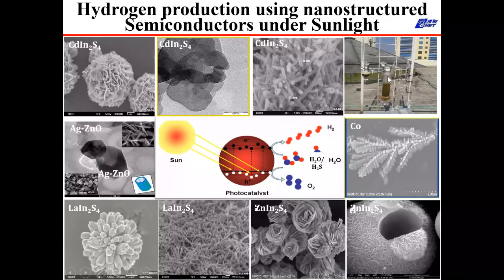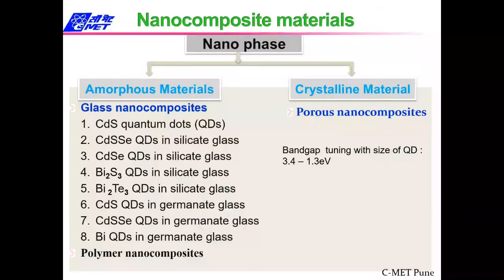And this is the... We also have, I will show you, one of the big reactors which we have in our premises. Then I told you we have the capability to produce nanoparticles in the glasses. So these cadmium sulfide quantum dots, cadmium selenide quantum dots, bismuth selenide, bismuth, all these are grown in the silicate glasses.